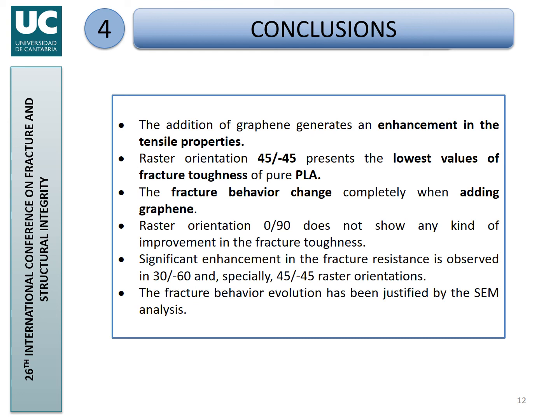This same raster orientation presents the lowest values of fracture toughness when working with pure PLA, but this changes completely when adding graphene, with 45/-45 raster orientation presenting the highest values of fracture toughness when adding the 1% weight of graphene.